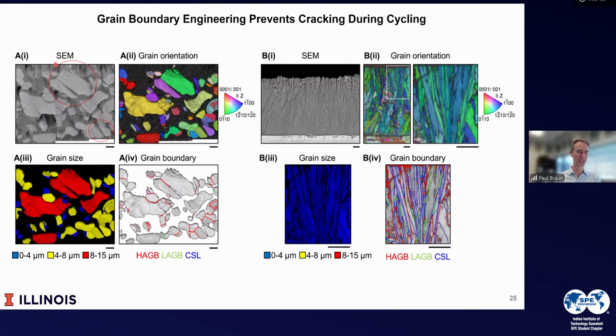And so if we look at SEM images after cycling, one sees that there is cracking again. You see lots of cracks running through this material. When we look at the grain orientation, you can see that the cracks occurred here where the grains had different orientations, because one grain was trying to expand one way, the other grain was trying to expand and contract the other way, and so it cracked. When we go ahead and do this in our electrodeposited material, because the grains all have basically the same orientation, that means we have a lot of low angle and coincident site lattice boundaries, and those boundaries have virtually no cracking present.